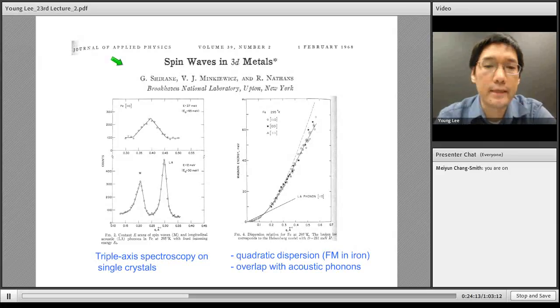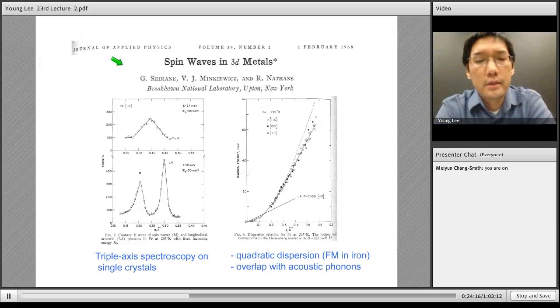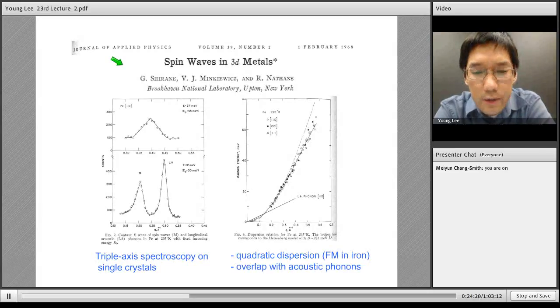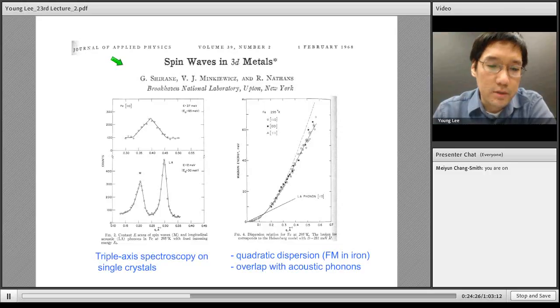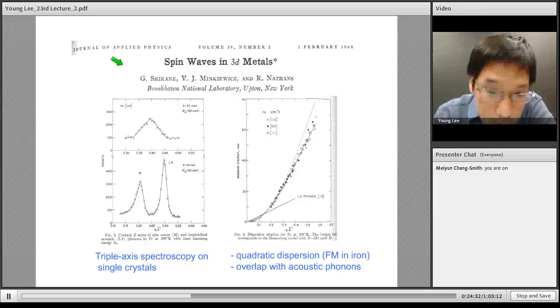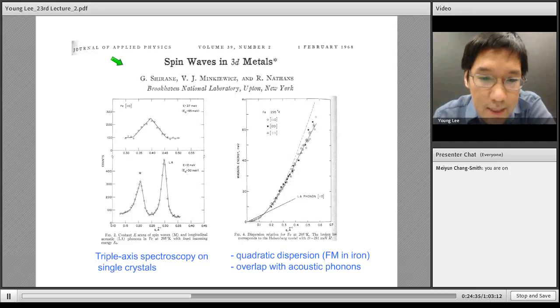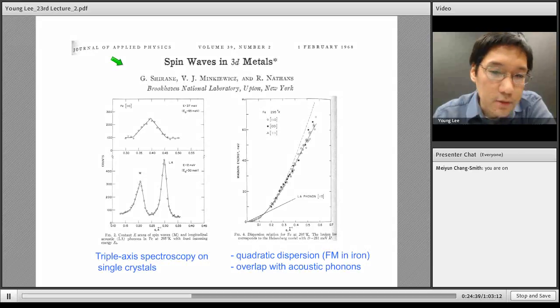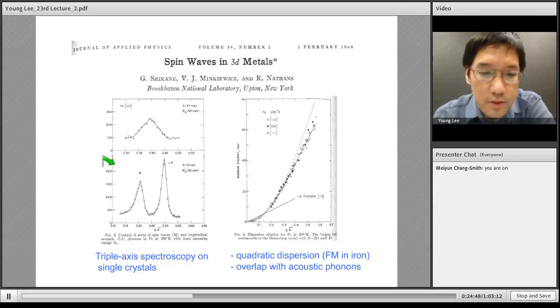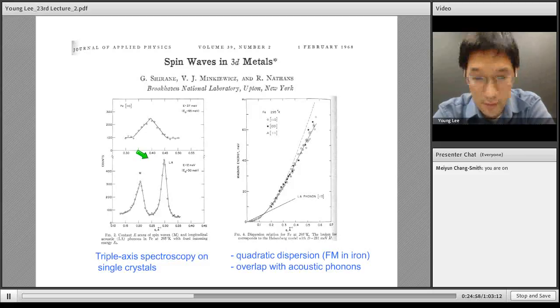Okay, so let's go to some data. Here's some early neutron scattering results on, I believe, iron. There are many other ferromagnets also in this paper by the Brookhaven group. This is triple axis spectroscopy, where they go to a certain energy, in this case, and scan Q. So these are constant energy cuts, and you can see these inelastic peaks. In this bottom panel here, you see two peaks, one labeled M, which is magnetic, and one labeled LA, which is the longitudinal acoustic mode. So you have both a spin wave and a phonon in the same scan.